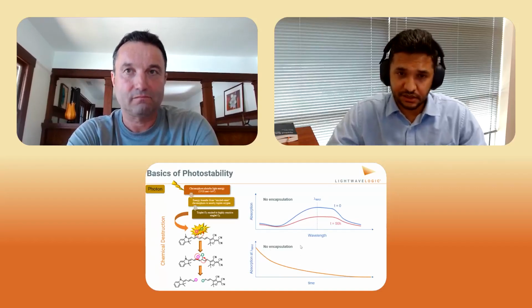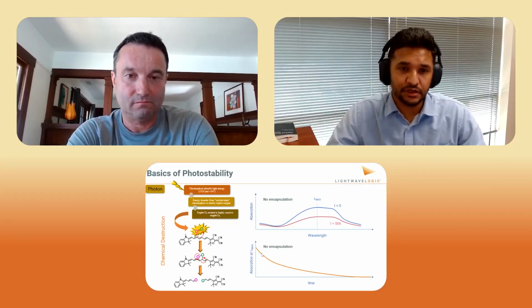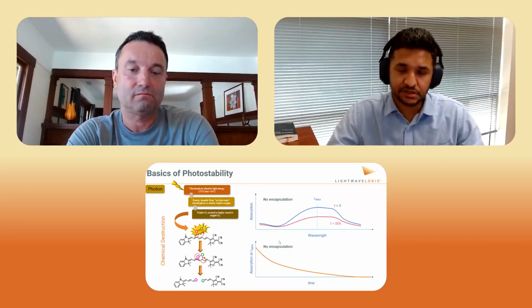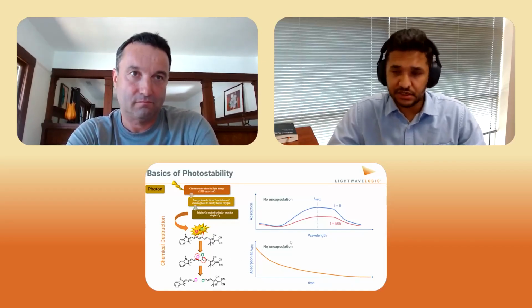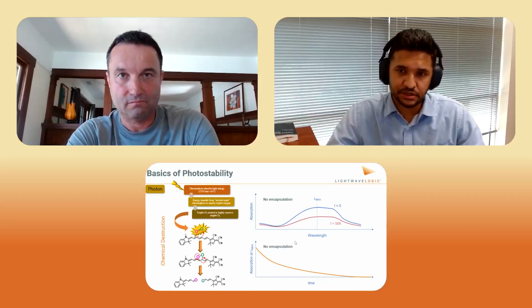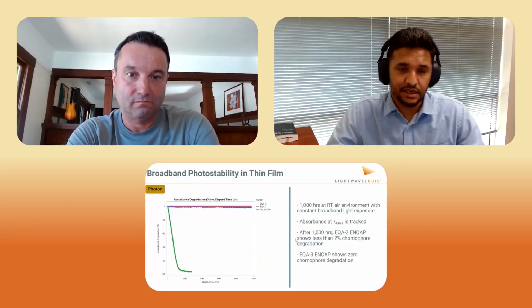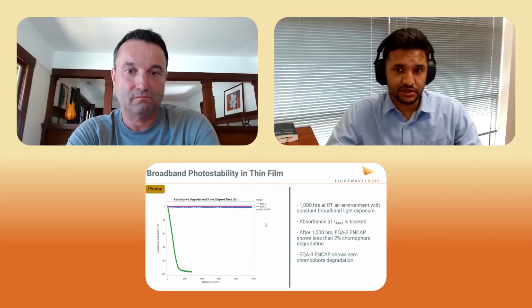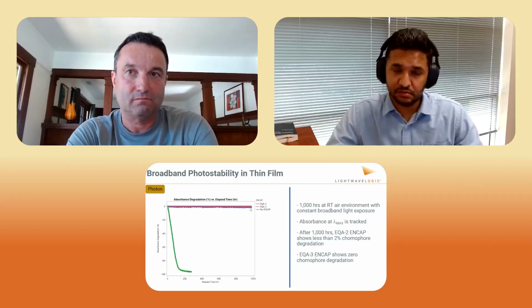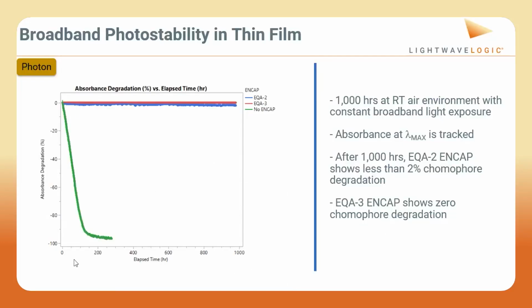So what we did here is engineer around this fail mode. We designed our own encapsulation for this application, and we tested with this encapsulation with the same amount of light. And what we observed is that generation after generation, our encapsulation is just getting better and better. Without encapsulation, you can see that the same peak that we track dies within a few hours. But with our encapsulation, there is no change. With our latest encapsulation, there is zero change.